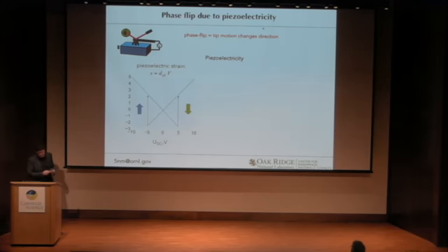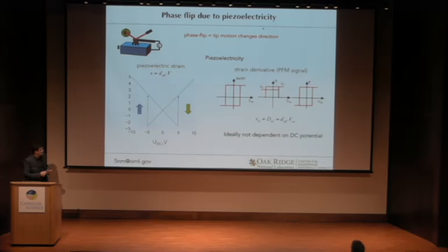And so if we had access to this piezoelectric strain all the time, in fact, this talk probably wouldn't be necessary, because this is a very unique property of ferroelectrics and a very clean signature of piezoelectricity. And so in that case, it's very well defined. But the problem is that the signal here is typically not strong enough for us to just get them in mass. So what we do is we take derivatives of this loop using lock-in amplifiers. And then the derivative of this will look like a nice square loop. And then we decompose it into amplitude and phase, and the phase flips where the ferroelectricity flips. So this is all well, and we all understand that.